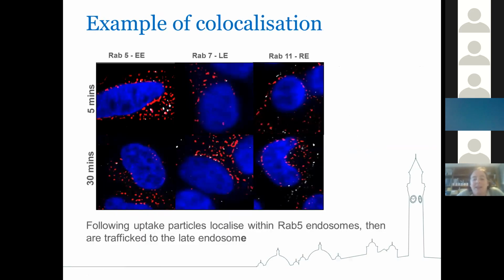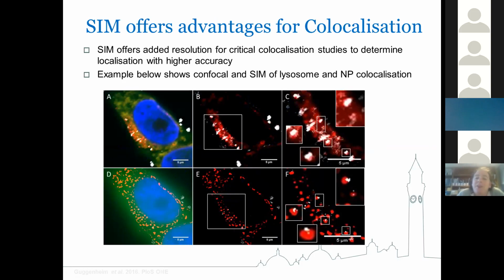And then we can really do the same sort of approaches where we can look at RAB5 for the early endosomes, RAB7 for the late endosomes, and RAB11 for the recycling endosome, and correlate where the particles are. So we could see a lot in the early endosomes by about 5 minutes, and less by about 30 minutes. And then by 30 minutes, they were increasingly present in the late endosomes and the recycling endosomes. And again, for the co-localization studies, the structured illumination microscopy offers us some advantages.